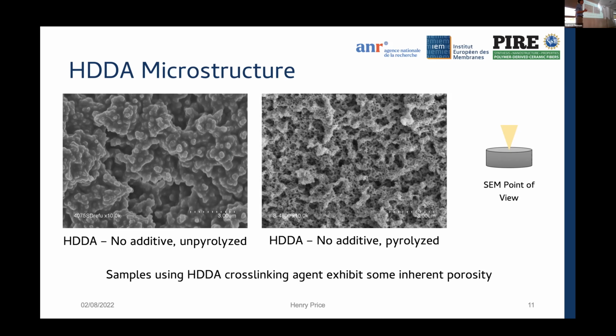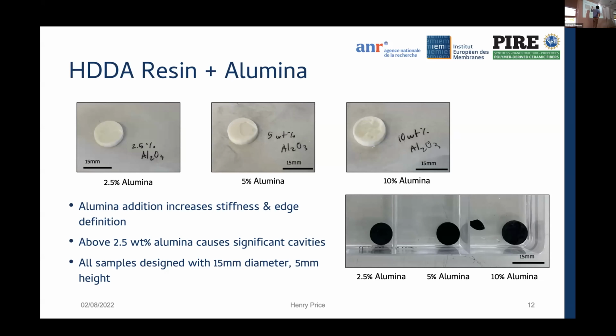It's a smaller powder, so more surface area to volume ratio. Also, I believe it was not spherical, so it could have had more surfaces to be caught on each other and increase that viscosity. Post-pyrolysis, these were generally more successful, but still, as they used this HDDA resin, they still had some delamination issues.